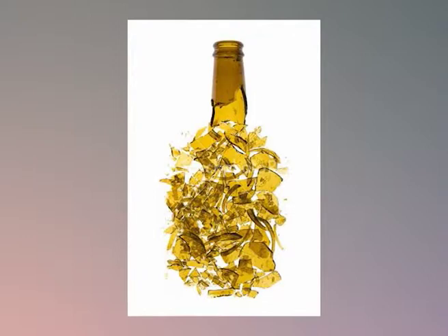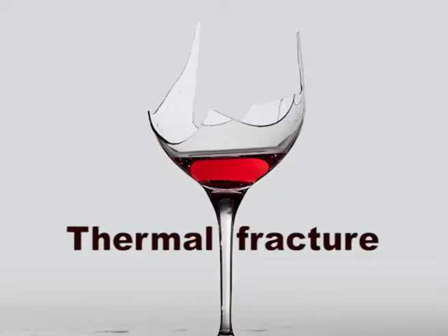After the initial fracture, it often forks at both ends, producing a series of fractures that are symmetrical about the initial longitudinal fracture, that is, in the form of a fan shaped pattern. As the fan shaped pattern diverges, it travels through the circumference and separates the neck and base from the rest of the portion. Then comes the thermal fracture.